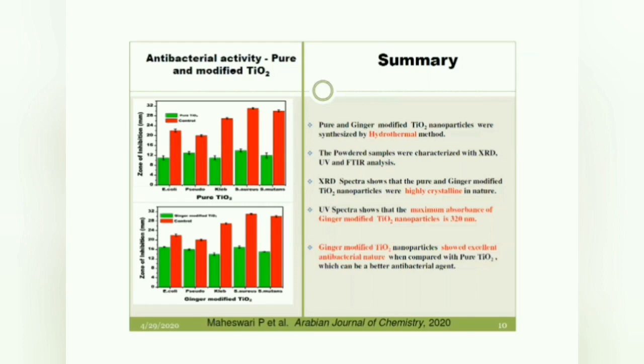So the summary of this whole thing is we have synthesized pure and ginger modified titanium dioxide nanoparticles using a hydrothermal method. The powdered samples were characterized with XRD, UV and FTIR analysis. The XRD spectra shows that the pure and ginger modified samples are highly crystalline in nature. The UV spectra also shows 320 nanometer for the ginger modified. So from this, I conclude that the gingerol in the ginger extract has enhanced after modifying it with the titanium dioxide nanoparticle. It showed an excellent antibacterial nature.